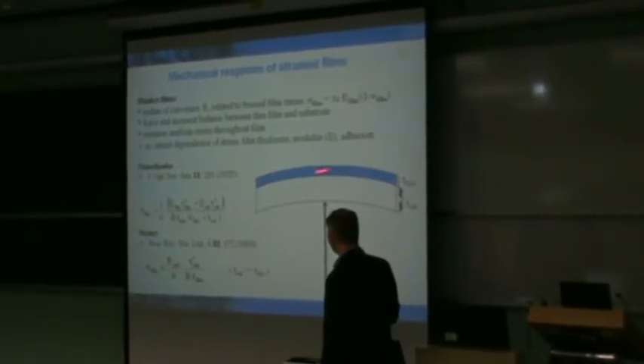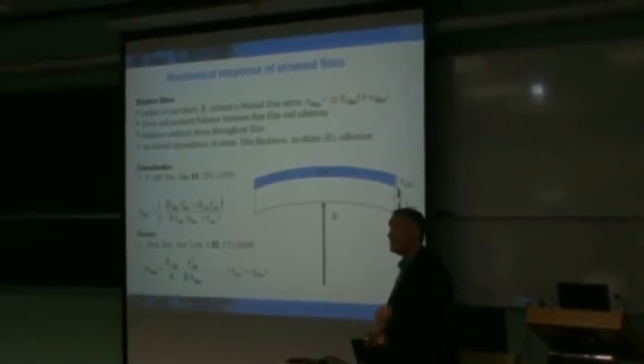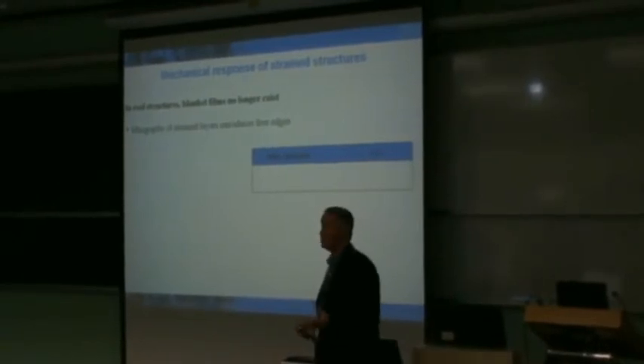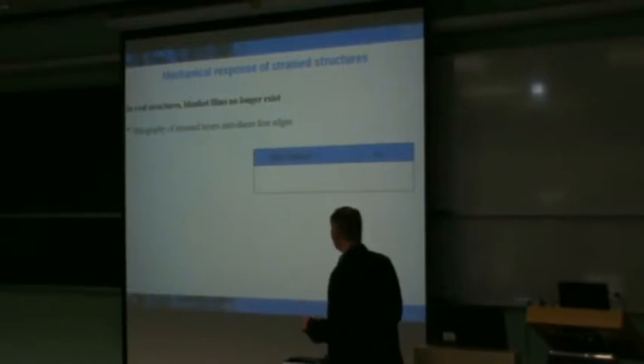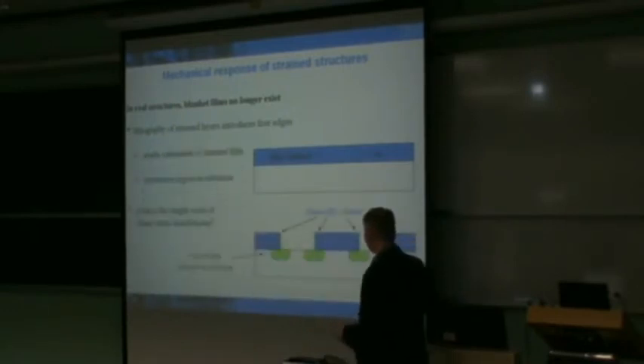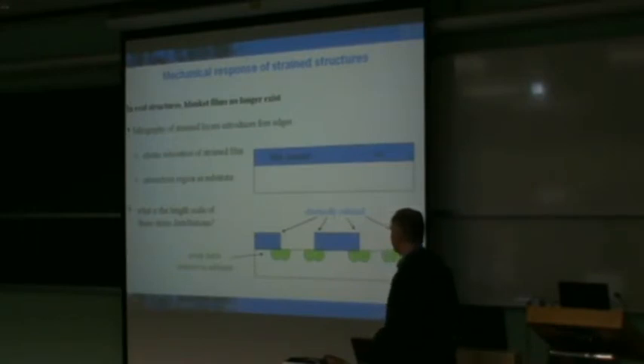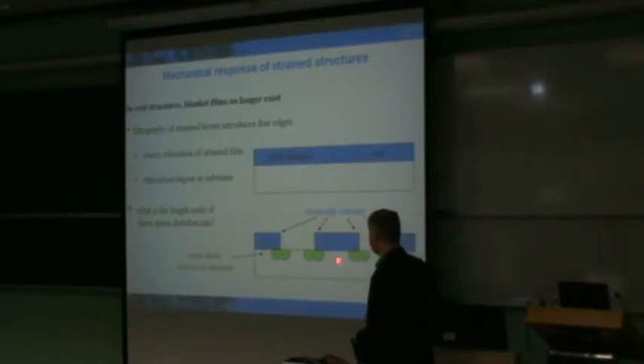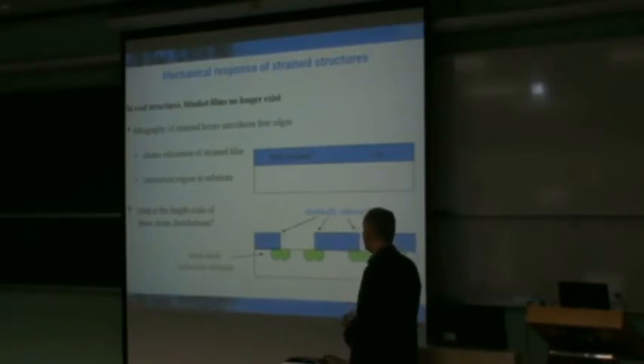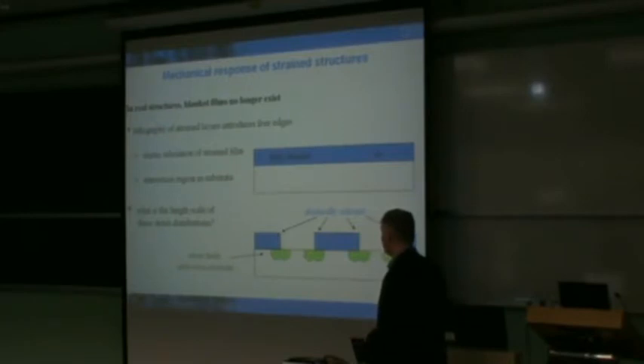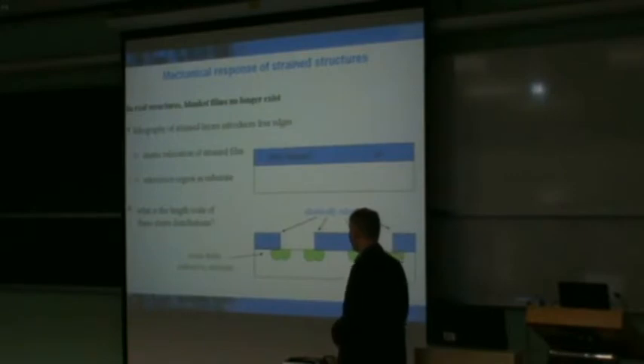But, of course, there are several assumptions that go into it. The fact that, clearly, for this to occur, we assume that there's uniform stress throughout this film, so that the elastic properties, thickness, and that you have perfect adhesion at all points on here, those all have to be in play. Well, in structures, clearly we don't have blanket films anymore. And the mere fact of incorporating edge effects, basically any time you remove these materials, you're changing the strain state of the system. And so you do see elastic relaxation, which is what you need to drive this behavior. But it is something that is definitely spatially localized. And you have to understand what the length scale of those strain distributions are. It's not necessarily something that comes from one dimension, but can come from different parameters.